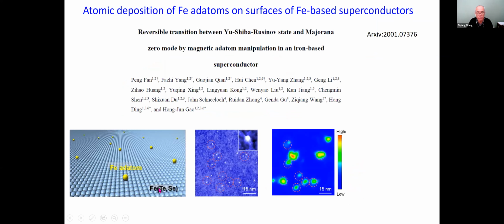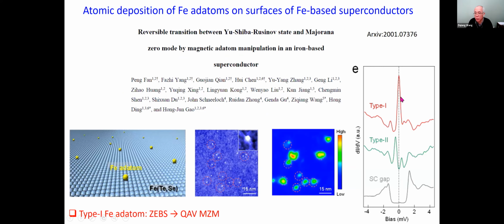Now, more recently, Hong-Jun Gao and Hong Ding's group at IOP deposited magnetic ions on the surface of FTS. Now, this is quite spectacular because now we see 2 kinds of iron atoms. There is what I call type 1 here that shows a zero energy peak, just like what we would anticipate from a QAV nucleated at the magnetic ion. We also see type 2 atoms. These guys show Yu-Shiba-Rusinov states, right? No zero energy peak. This is actually parallel to what you see in adding a magnetic field. You see both topological vortices and non-topological vortices.